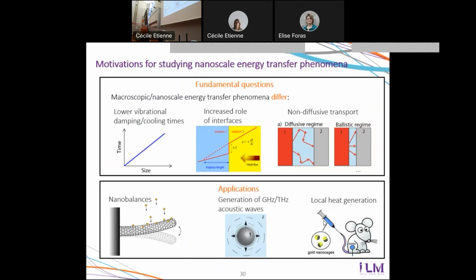Another specificity of nanoscale heat transfer is that when you work on very small objects, in some cases, the size of the object can become smaller than characteristic lengths of the material. For instance, the phonon mean free path, the typical length over which a phonon can propagate before encountering a collision. When this happens, it means that the thermal transport cannot be assumed anymore to be diffusive with many collisions. We enter another regime, which is called the ballistic regime, in which there are far fewer collisions. So all this constitutes fundamental motivations for investigations of heat transfer phenomena at the nanoscale.